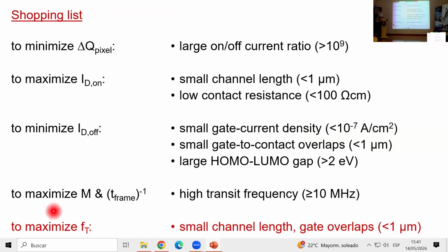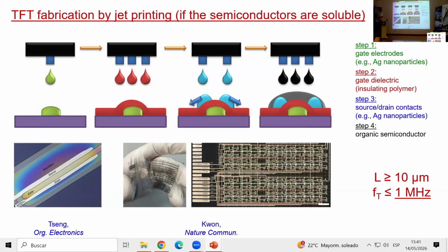Okay, so a final item on our shopping list here: to maximize the transit frequency, we need to have a very small channel length, very small gate overlaps, less than 1 micron. So nanoscale transistors, or else we'll never make it. And it's immediately clear that inkjet printing, for example, is never going to make it, right? So with inkjet printing, it's possible to make fantastic organic transistors. So this is a photograph of an organic TFT fabricated entirely by inkjet printing, and this is a photograph of a 10 by 10 centimeter square array of integrated circuits based on organic transistors fabricated entirely by inkjet printing. All the layers deposited and patterned by inkjet printing. Beautiful circuits, device, everything functional, except with inkjet printing, the lateral resolution is necessarily on the order of 10 microns, not below 10 microns. And so the transit frequency will never be above about 1 megahertz, much less 10 megahertz.